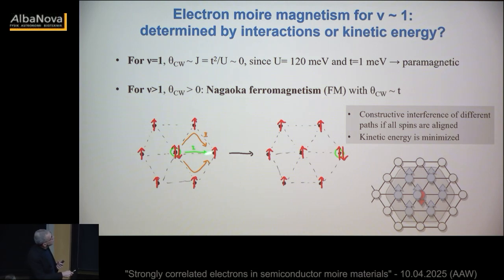Now, that would mean that different paths for this doublon hopping onto neighboring sites have to interfere constructively. Right? This is only possible if all the spins are pointing in the same way. Right? So if this spin were pointing down, then hopping from the top and hopping from the bottom will leave a different final state and the interference will be imperfect. So this is the idea of kinetic magnetism: to minimize the kinetic energy, it is favorable to polarize the spins because there is no other energy scale. The anti-ferromagnetic interactions are so weak that you do not have to worry about them. Okay? So this is the picture.